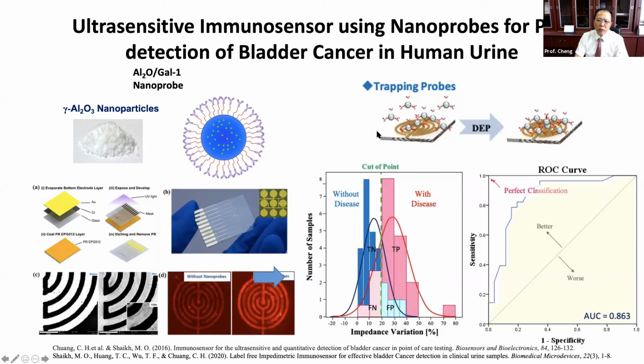The first step is that we need to immobilize this nanoprobe onto the electrode. So we use the dielectrophoresis process. With this dielectrophoresis force, we just apply an AC voltage, then the particles will move and stick onto the electrode. You can see this is before we trap the nanoparticles. The electrode is very blank and clean. After we trap the nanoprobe onto the electrode by using the DEP force, you can see the dark parts are the nanoprobe on the electrode. And we can also confirm this by the fluorescence image.